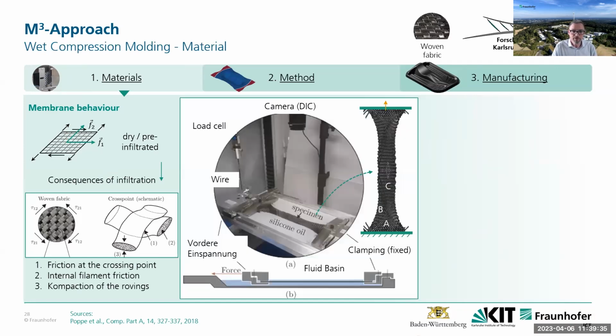So infiltration determines the shear behavior, influenced by the friction between and within the contact points of a fabric, as illustrated here on the left side. The consequences of infiltrations are that friction changes, both at the crossing point and within the rovings. In addition, the compaction behavior is changed, and that influences the locking angle.